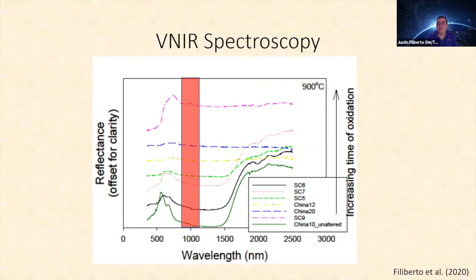And so what this is telling us is we're going from olivine to flat spectra, which is consistent with magnetite, going to hematite as we go to more and more oxidation. So if this is applicable to the previous results, that the high 1 micron emissivity modeled for lava flows on the surface of Venus is caused by olivine, our results suggest that these flows are months to years old and volcanically active. However, this is for olivine only, and lava flows are made up of a lot more things.